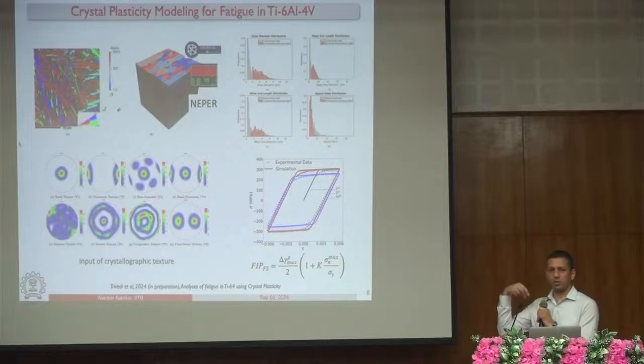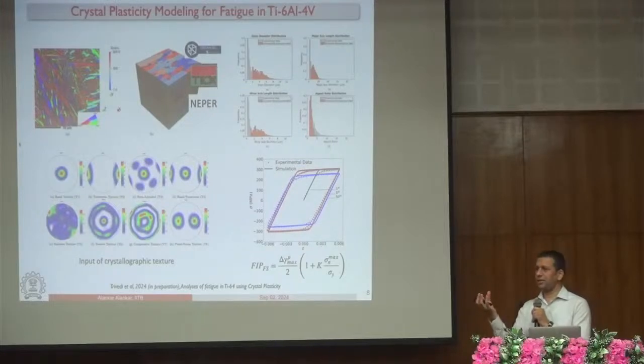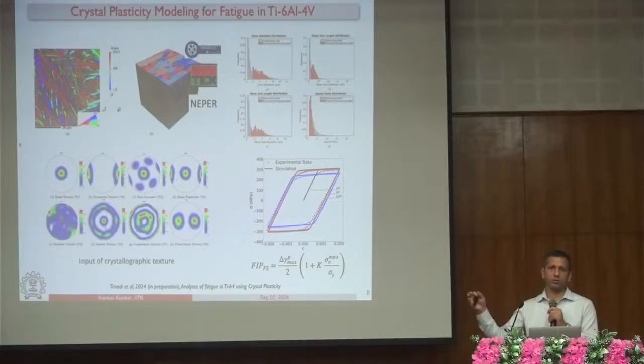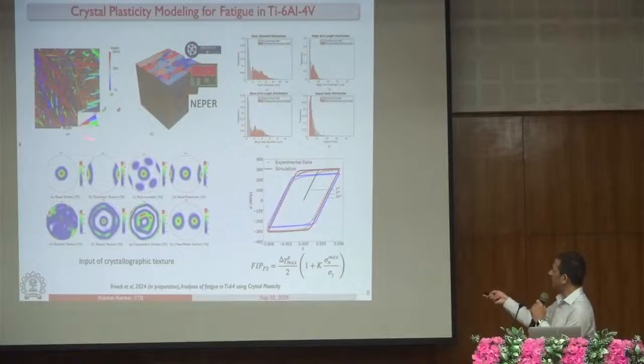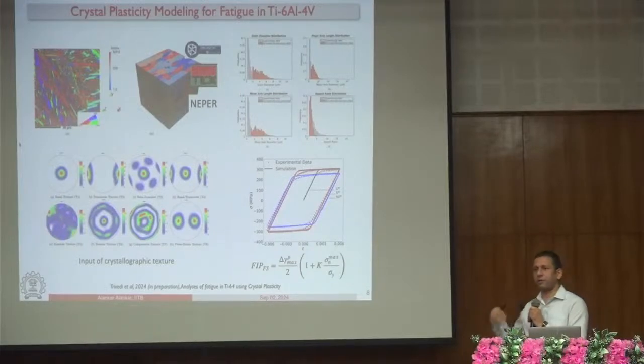If you cool it down slowly, you will see equiaxed grains, some chunks of beta phase along the grain boundaries, but in this case, it has been cooled quickly, so there are lamellae of alpha and beta. Some of these may actually have even finer structures of alpha beta layers at nanoscale and microscale, right? So this has been scanned in SEM using the EBSD method, and then that statistics has been used in Dream3D, or you can use MTEX, which are open source programs, and this synthetic microstructure has been created.